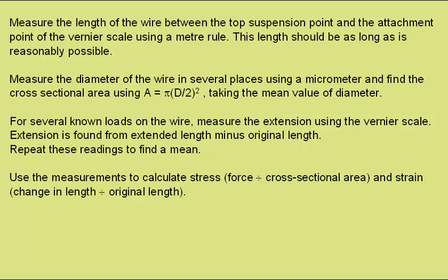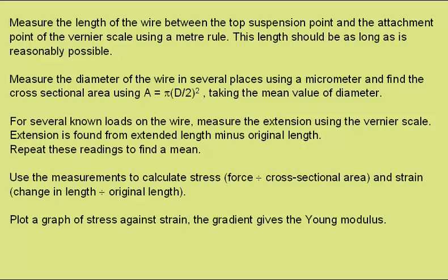Using the measurements to calculate the stress as force divided by cross-sectional area, and the strain as change in length divided by original length, we can then plot a graph of stress against strain. The gradient of this graph gives the Young's modulus we're expected to find.